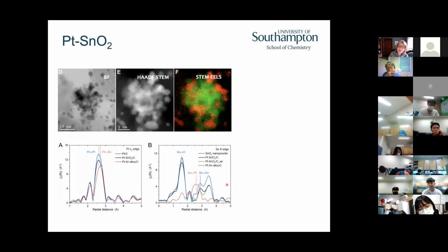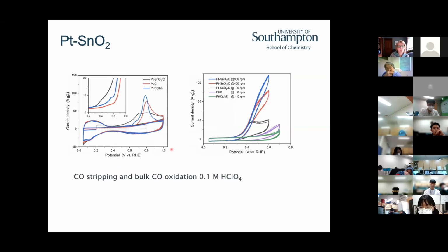When we looked from the perspective of the tin oxide decorated sample, so here's what the sample looks like. You can see the platinum with the tin oxide particles. When we look from the perspective of the platinum, it is really just platinum particles. We look from the perspective of the tin, it's tin oxide, right? Again, we still see the effect though, in terms of the enhancement of the CO oxidation, right? And we can see that again, it can be sustained,